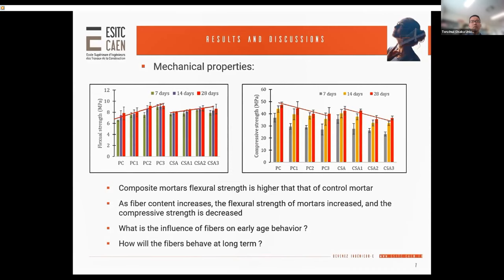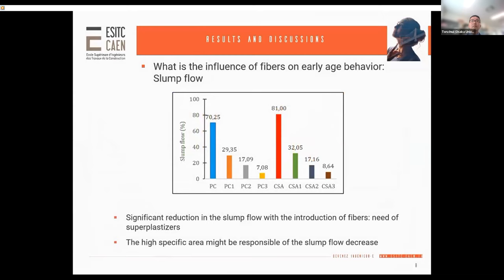As you can see also from the results, whatever the age of mortar, the toughness index that has also been calculated, the toughness index of the control and the 1% fiber reinforced mortar, is always equal to 1. So what is the influence of fibers on early age behavior?